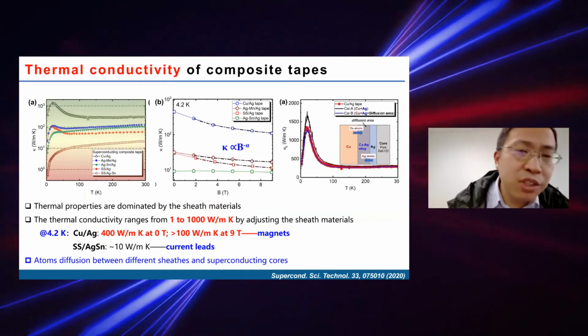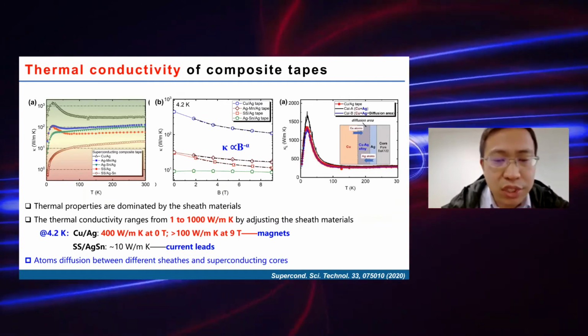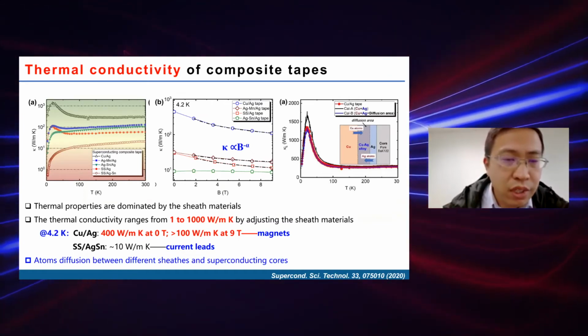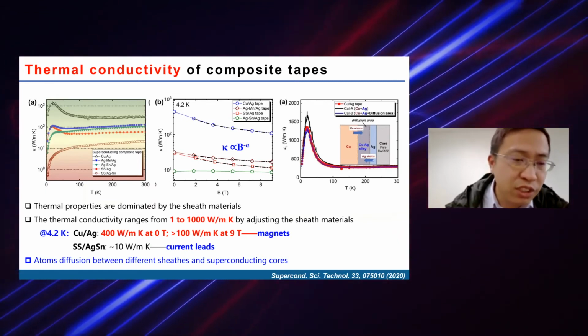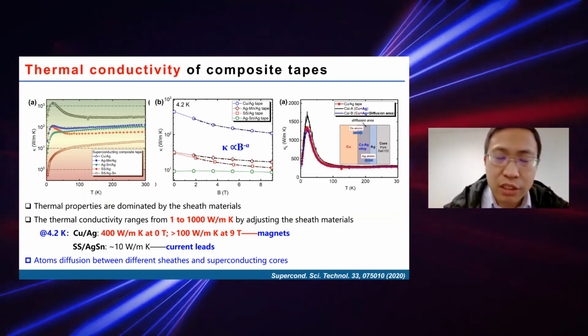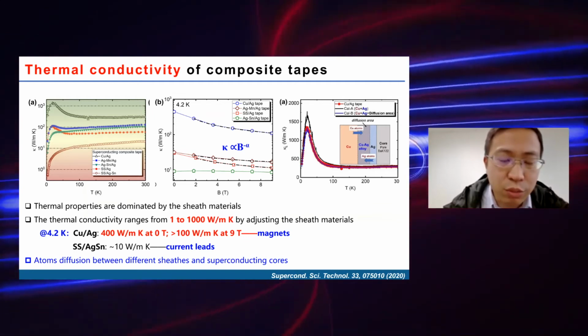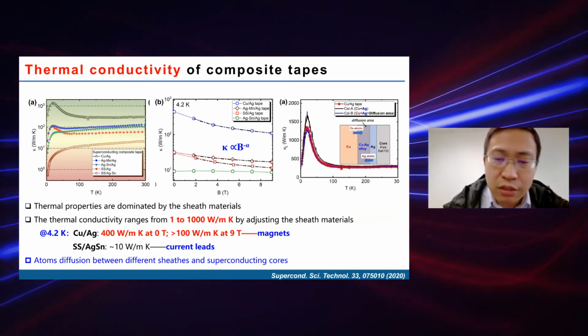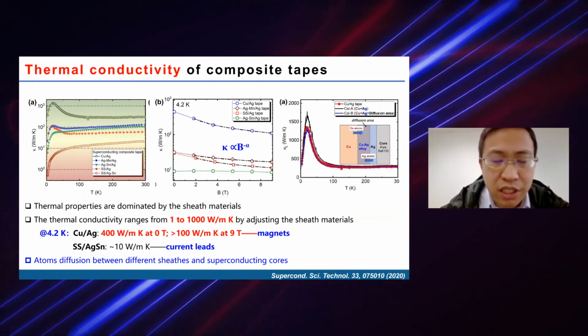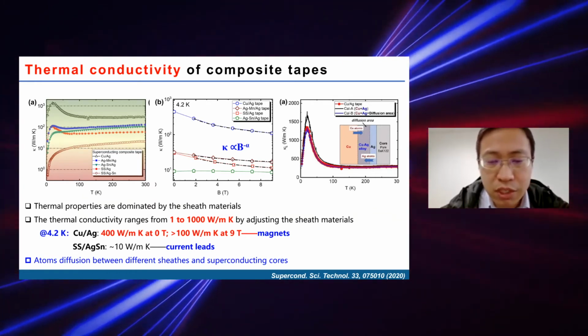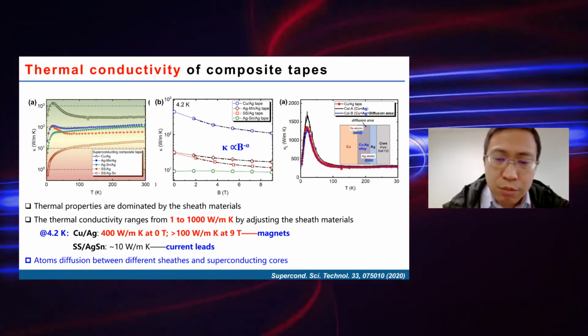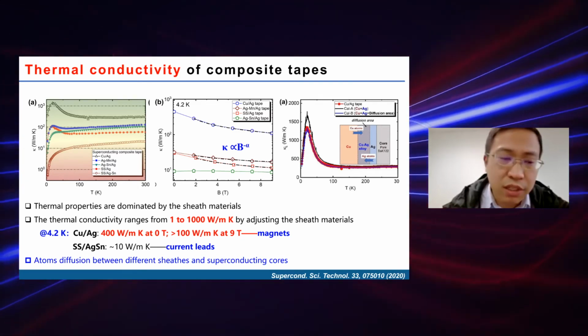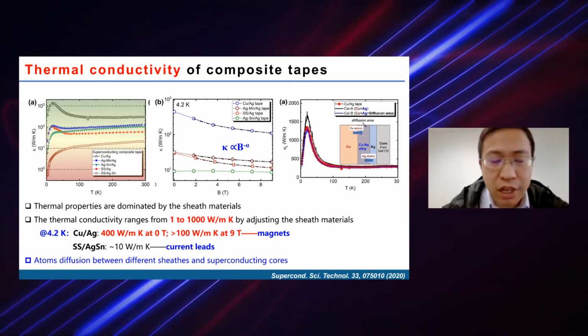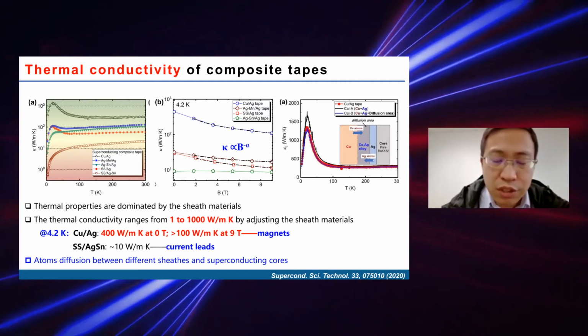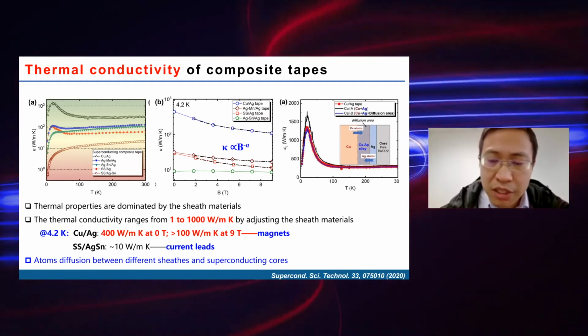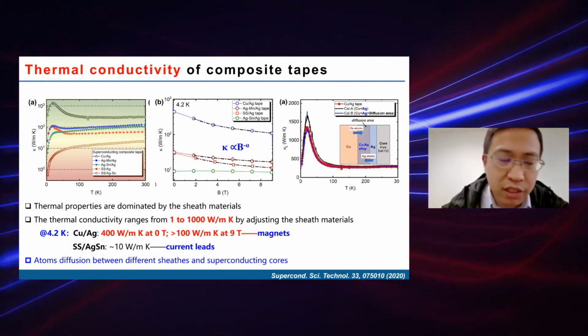And thermal conductivity is also very important. We measured different composite tapes and found that the thermal conductivity of iron-based superconducting tapes is actually dominated by the sheath material. We can adjust the thermal conductivity from 1 to 1000 watt per meter Kelvin by adjusting the sheath material. And copper silver has a very large thermal conductivity and is very cheap to apply in high field magnets.